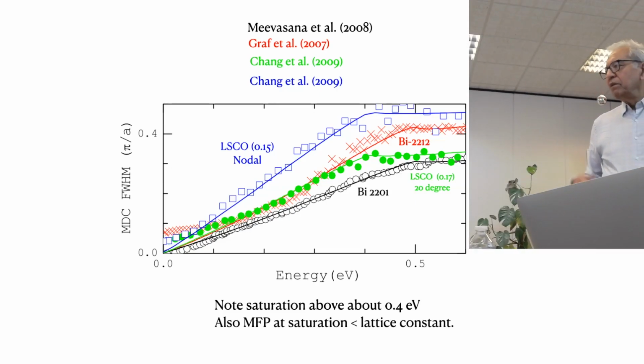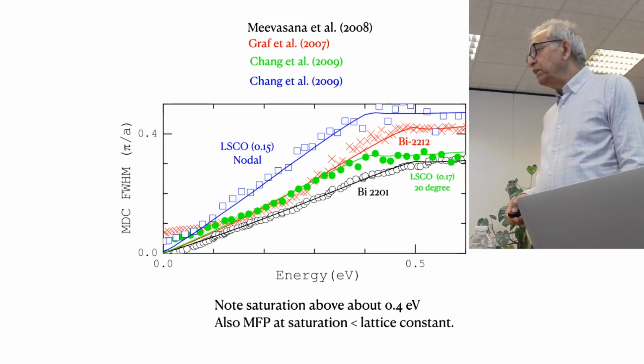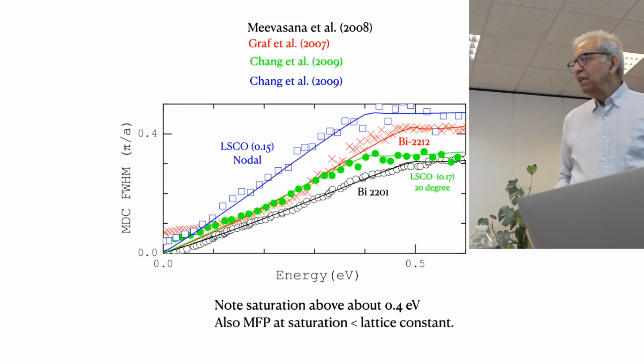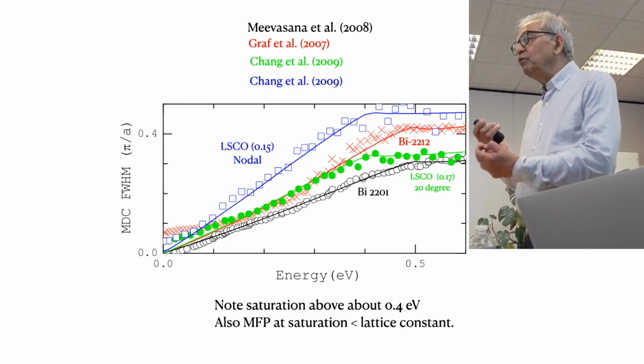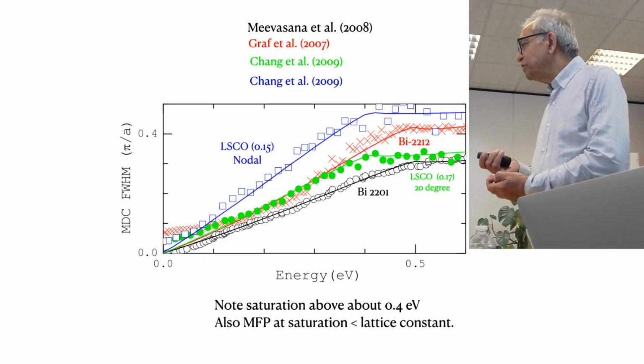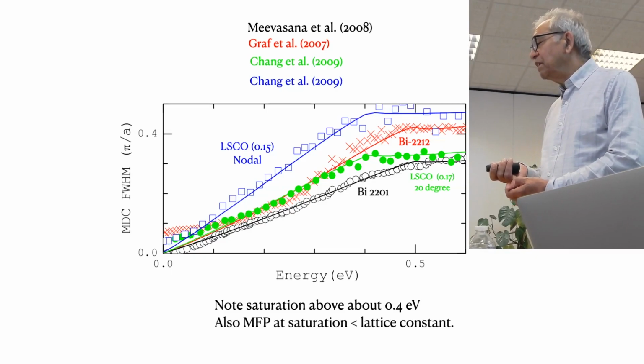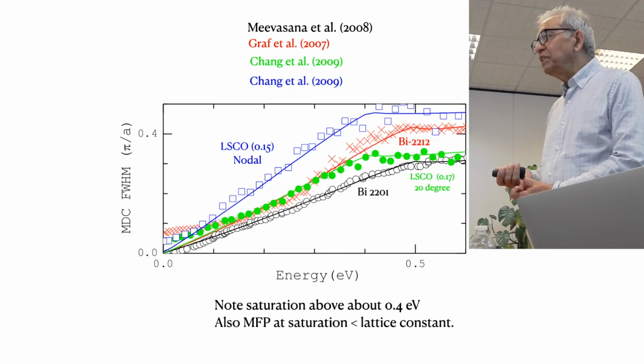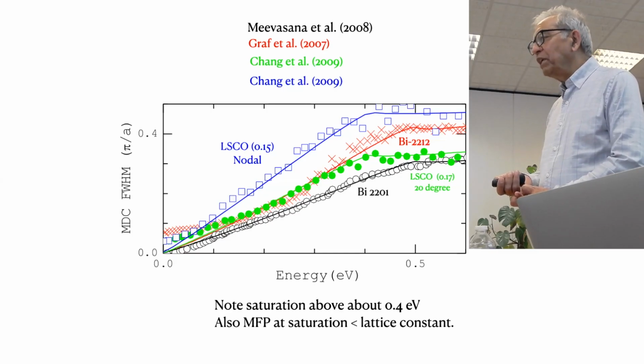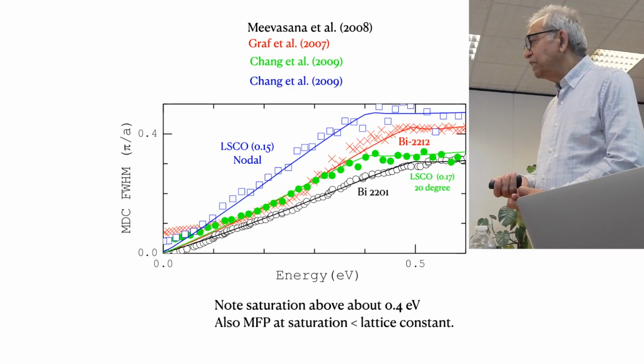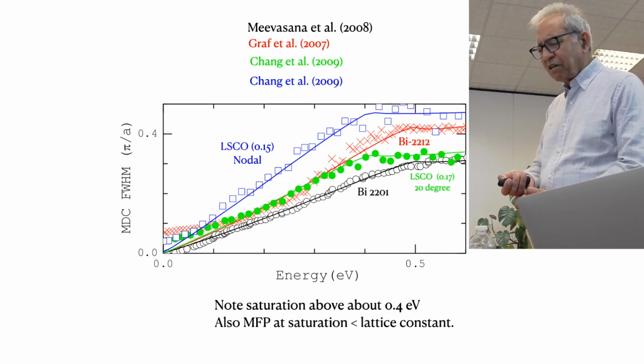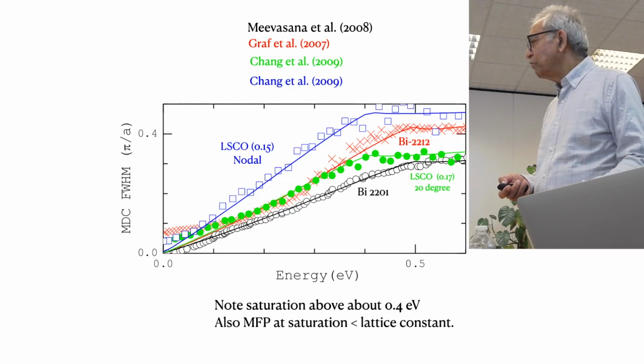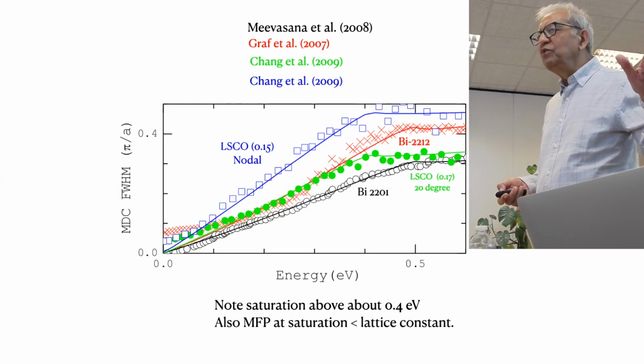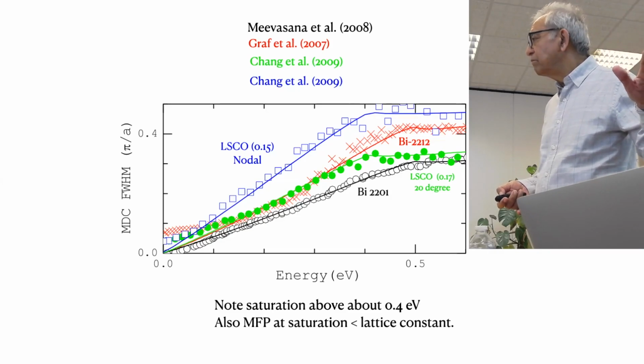Okay, so the important point I want to make is that with these 2 parameters, I can get you the coefficient of the linear heat capacity, the coefficient of the linear resistivity, the coefficient of 1 over omega of the conductivity, and a couple of other properties. It's in a Reviews of Modern Physics article in terms of these 2 parameters, okay? Quantitatively.